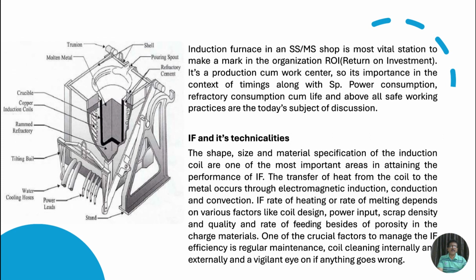The shape, size, and material specification of the induction coil are among the most important areas in attaining the performance of the induction furnace. The transfer of heat from the coil to the metal occurs through electromagnetic induction, conduction, and convection. The IF rate of heating or rate of melting depends on various factors like coil design, power input, scrap density, quality and rate of feeding, besides porosity in the charged materials. One of the crucial factors to manage IF efficiency is regular maintenance, coil cleaning internally and externally, and a vigilant eye on anything going wrong.